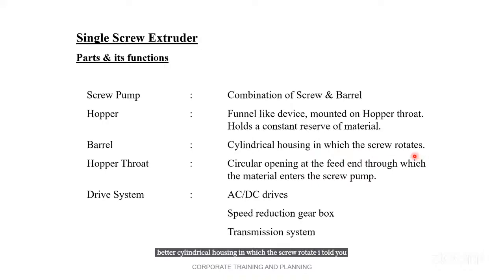I told you the barrel is not very strong like the injection molding barrel. The injection molding machine barrel is a higher pressure barrel because there may be at least 35,000 psi, pounds per square inch, of pressure developed inside, and therefore the barrel should be resistant to such high pressure. It should withstand such a high pressure. But in this case, the barrel of the extruder is not as strong as an injection molding barrel.